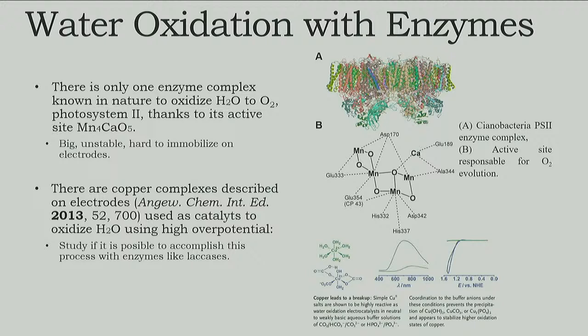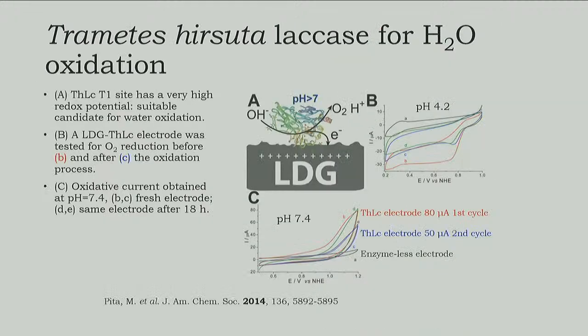And we said we have an enzyme that has copper inside. Its active site is copper, so maybe it works. There is some kind of intuition here, and we said, okay, let's see what we find. We immobilized the enzyme here at neutral pH and applied very positive potentials. We can see here how it worked. This is the enzyme we have been using the whole time. The initial reaction, this is the oxygen reduction reaction that we use as a tester to see how the enzyme is performing. And then we put it into the oxidation cycle, and we see that we have this big current here. Later, the life of our enzyme has decreased by half, so we're affecting our enzyme with these large potentials. But after 18 hours, we could still get back some of the activity.